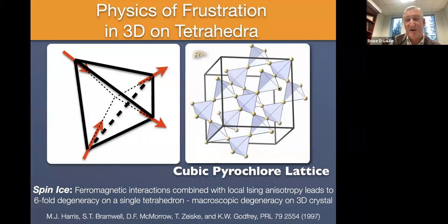And then you take those tetrahedra and you connect them together in 3-dimensional space with this pyrochlore architecture. And you get a degeneracy that actually scales as some power of the system size. So you get a degeneracy that very quickly gets bigger and bigger as you make the system size bigger. And that's referred to as a macroscopic degeneracy. And it can generate an entropy which is large enough to preclude the formation of an ordered state at low temperatures. There's just too many choices for the spins. And so there's a finite entropy in the ground state, and the state is classically disordered, okay?